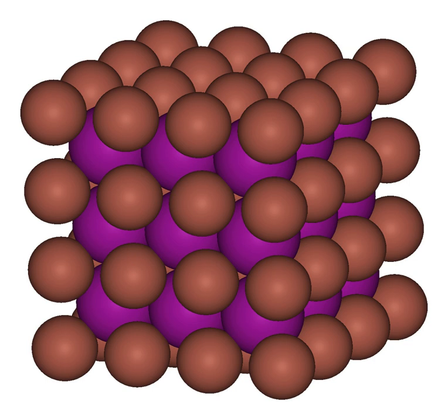Thallium III fluoride. TlF3 is a white crystalline solid, melting point 550 degrees Celsius. The crystal structure is the same as YF3 and beta-BiF3. In this the thallium atom is 9-coordinate, tricapped trigonal prismatic. It can be synthesized by fluorination of the oxide, Tl2O3, with F2, bromine trifluoride or SF4 at 300 degrees Celsius.